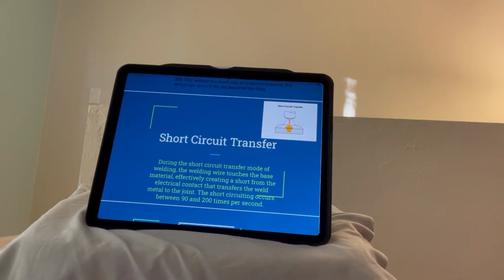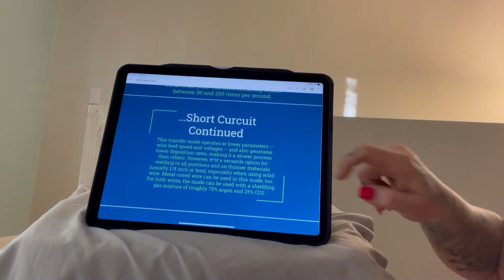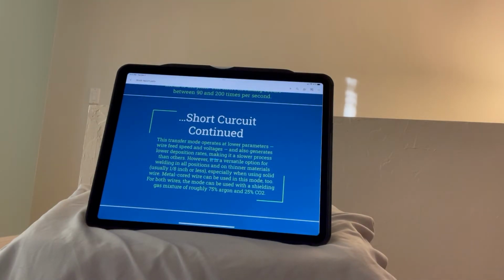Short circuit transfer. During this transfer, the welding wire touches the base material, creating a short from the electrical contact that transfers the weld to the joint. The short circuiting occurs between 90 and 200 times per second. This transfer mode operates at lower parameters, wire feed speed, and voltages. Generates lower deposition rates, making it a slower process than others. It's versatile for welding in all positions and on thinner metals.